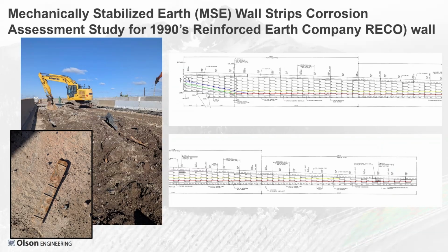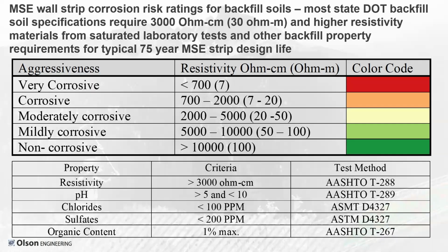So before we got involved in the project, they'd done some additional testing. I'm not showing those results, but they also looked at not only the laboratory resistivity, which when you do this type of testing initially on the backfill soils, you saturate them, do a laboratory test, and get the lowest resistivity to find out the most corrosive conditions, assuming it could become saturated in the future. But they also tested for pH of the existing soils. They'd done some limited laboratory resistivity tests of the backfill soils when they excavated them. And this was over about 30 years later that this occurred. And they found some pH problems. It was out of the range, and there's obviously pHs that are more lower or more acidic, leading to corrosion of the zinc, and it serves as a sacrificial protection layer.